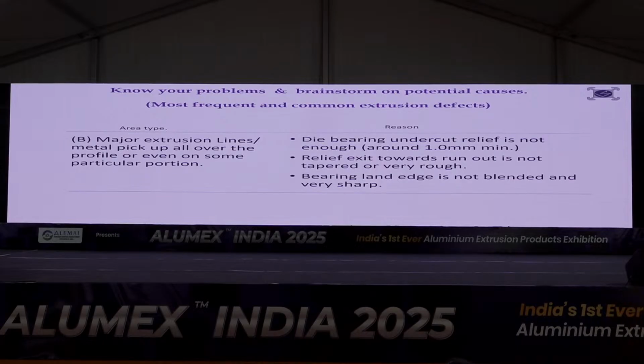Second thing is the bearing land area is not blended and is very sharp. When we cut a die, usually we try to balance the flow with the resistance. And that resistance we create either from the feeding pocket side or porthole side, or by increasing or decreasing the bearing length. So when we have a very abrupt change of bearing length, that blending is very, very important. We just can't do that. Some area will have 5 mm bearing and the adjoining part will have 2 mm bearing and there is a step. So there will be problem. That creates a flow due to choke and relief creation during the hand polishing. And if it is uniform, at least with the hand polishing also, the polishing will be more or less uniform.